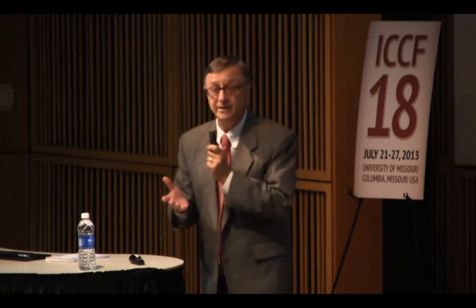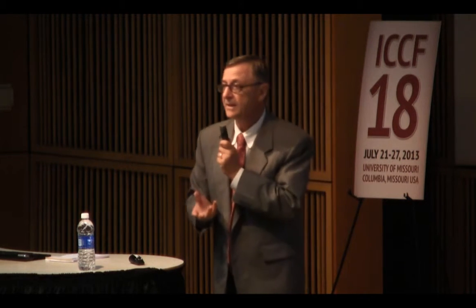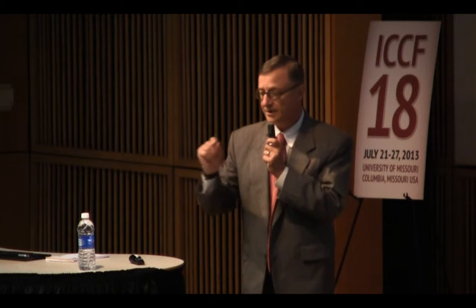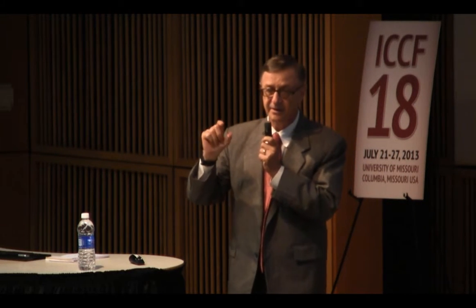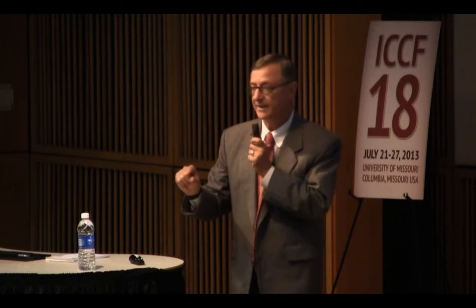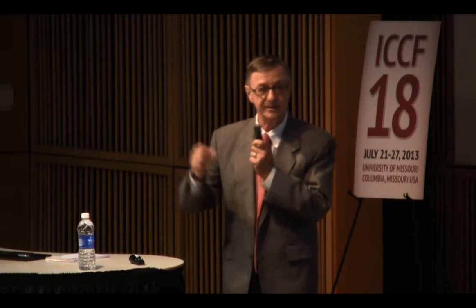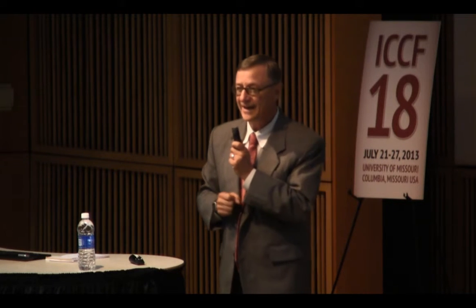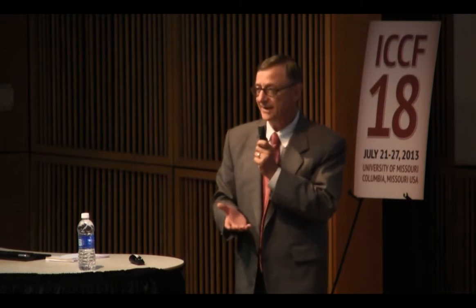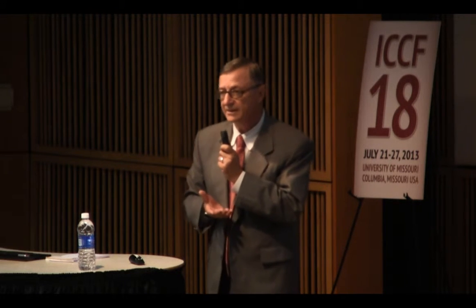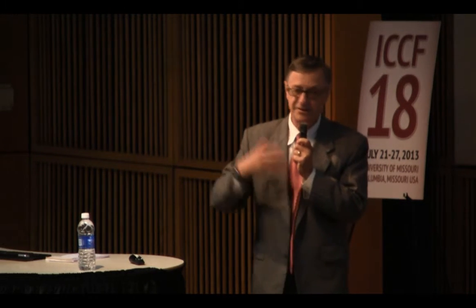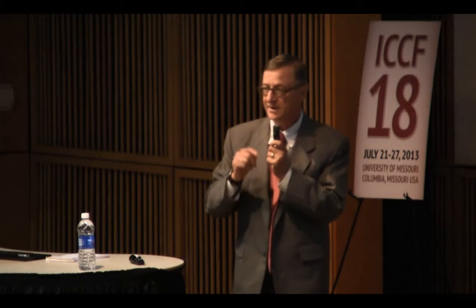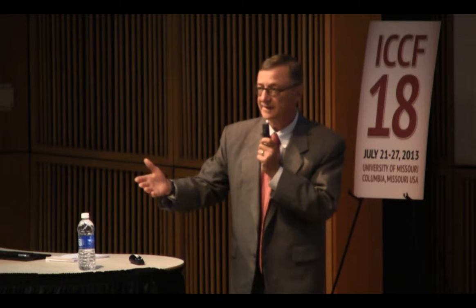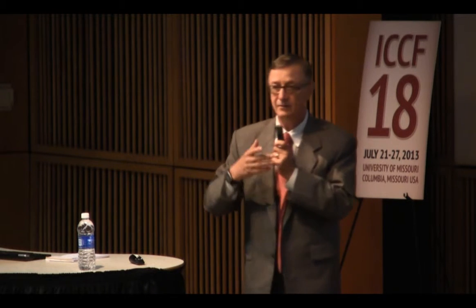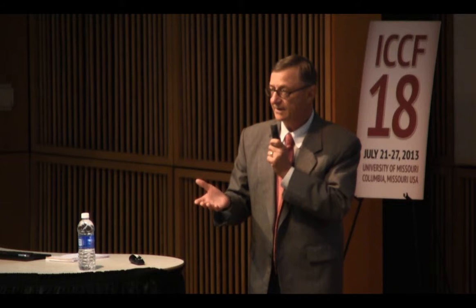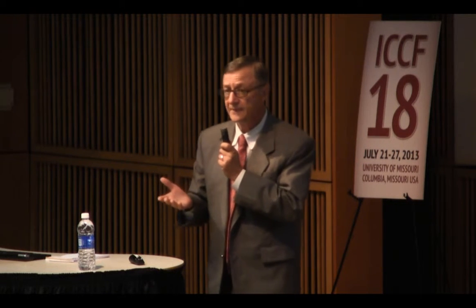Then what we didn't know to tell the metallurgists at the time was that when these are rolled, often 1 millimeter palladium is rolled down to 100 microns, or maybe even 50 microns in one roll. Now that is elongations of thousands of percent or something. And when you look in the metallurgy literature, when people study elongations, it's 2, 3, maybe 10% or something to see what the structure does. So when you anneal this, you really are starting out with extremely highly defective material.